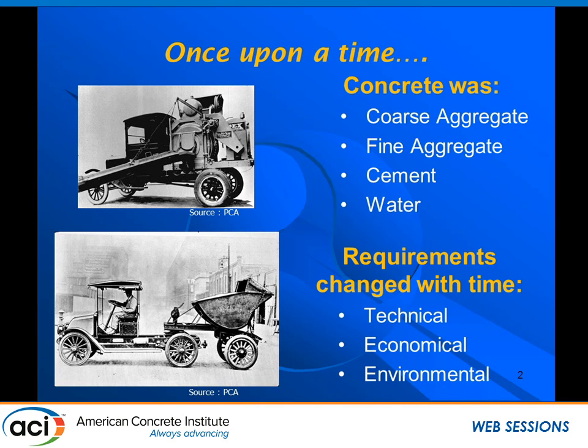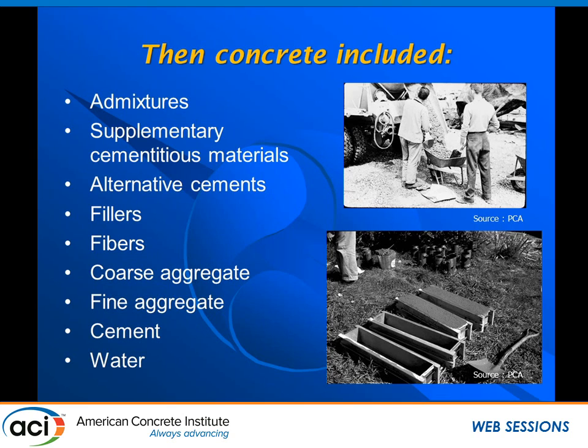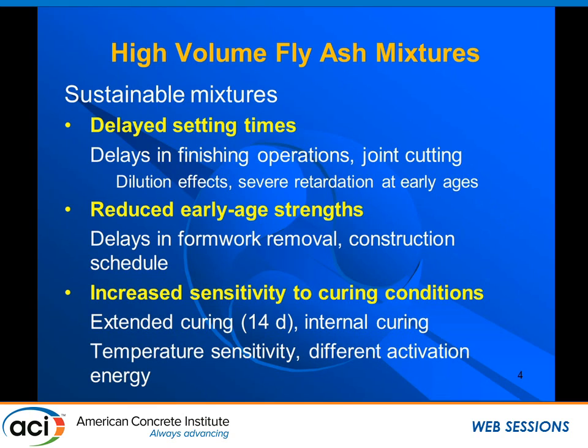Since then, the technical, economical, and nowadays the environmental requirements have changed quite a lot, and we got to a bunch of different things that drive us nuts in the field. So we have admixtures, supplementary cementitious materials, fillers, fibers, and our conventional concrete. Nowadays we have been trying to push the envelope more to use high volume fly ash mixes. We are not quite there yet, but we have to overcome some challenges first: delayed setting, reduced early age strengths, and increased sensitivity to curing conditions.